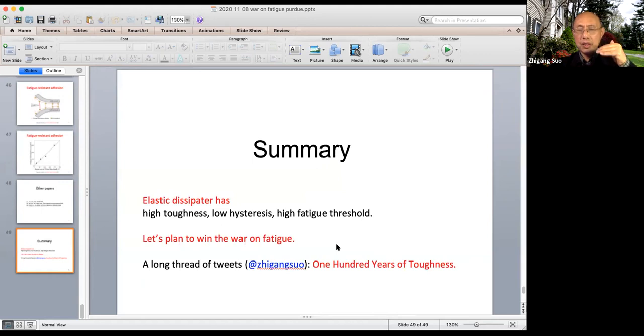I think in recent years, we cracked this open with this simple idea, the elastic dissipator. So with the elastic dissipator, we already demonstrated it with a few materials. I showed you one in detail, but we demonstrated several materials. It shows high toughness, very low hysteresis, and an extraordinary, unheard-of high fatigue threshold for any materials.